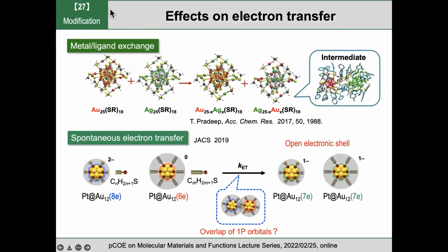Okay, so this is another example, the effect of electron transfer. In this case, the ligand is also important. As we already heard from Professor Pradeep, the clusters in solution exchange metals and ligands. So they are rather dynamic, as reported by Professor Pradeep. And we recently found that electrons can be transferred spontaneously between the clusters. So this is the electron transfer we discovered.